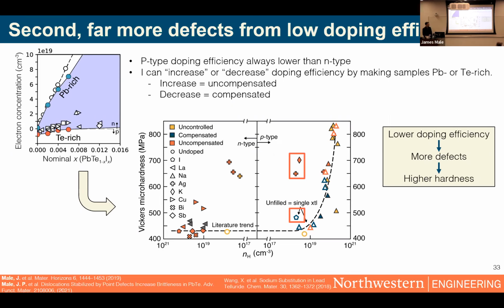A couple of highlights to demonstrate this point further are the potassium and silver P-type dopants here. They have lower doping efficiency than these sodium dopants and correspondingly are more brittle. And also here I have an iodine-doped sample that I enabled to be P-type by making it tellurium rich. That gives it a ton of vacancy defects, which have made it harder than any other iodine sample I've observed in the past or anyone else has reported.